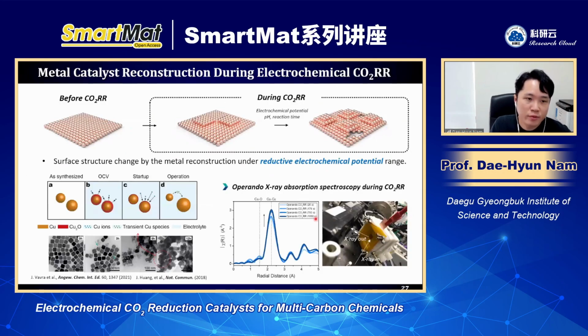As I mentioned, it is very important to understand the reconstruction because although we fabricate the catalyst surface, during the CO2RR the surface structure can be changed, because this is also related to the electrochemical potential, the pH of the electrolyte, and the reaction time. So this is the general mechanism of how this reconstruction occurs. When the catalysts are in contact with aqueous electrolyte, there can be dissolution of metal ions into the electrolyte. And then if we start to apply a reductive potential, these dissolved metal ions can be redeposited onto the surface of the catalyst. This is how this reconstruction can occur.